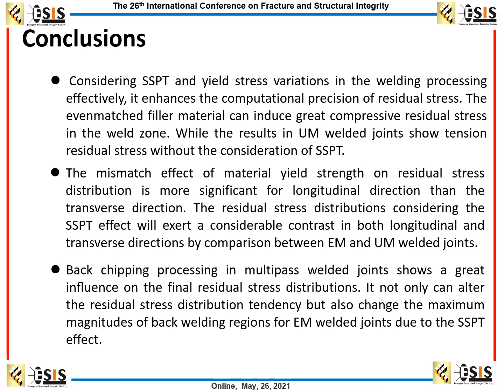The third is that the back chipping processing in the multipass welded joint shows a great influence on the final residual stress distribution. It not only can alter the residual stress distribution tendency, but also change the maximum magnitude of back welding regions for the EM welded joint due to the SSPT effect.